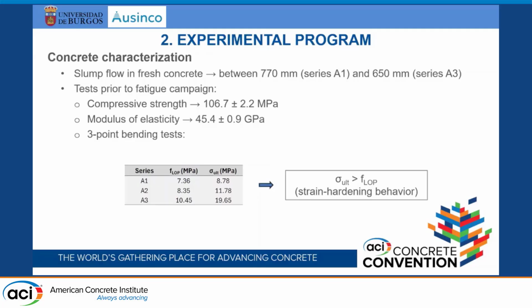Okay, so what you can see here is the ultimate stress is higher than f_LOP in all cases. So what this means is that in all series we find a strain hardening behavior. This is, once the specimen is cracked, the fibers are able to withstand more load than the matrix itself. So that's important to keep in mind for later.